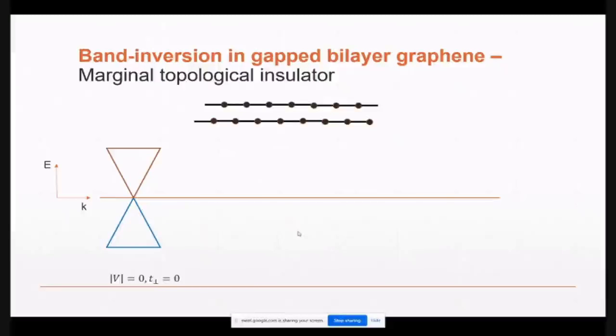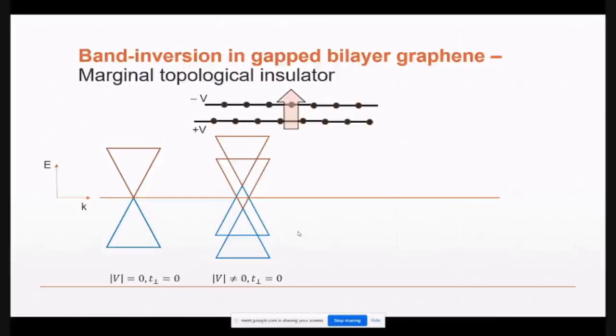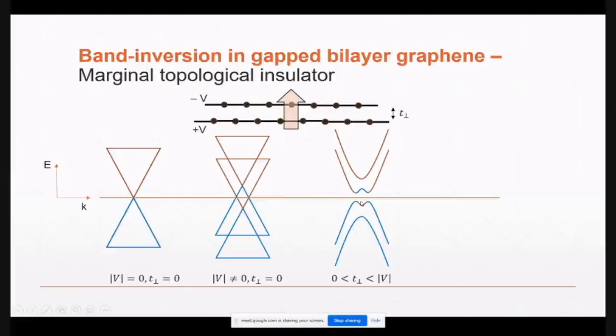For example, you take two layers of graphene, but they are decoupled from each other. Each has a conical band structure, but then you apply an electric field, say, and you shift them because you create a voltage difference between the two. And then you turn the interaction on. If you turn the interaction on, you can create these hybridizations, and then you gap out. Not just do you gap out the bilayer graphene, but you can also see at the bottom, a part of the conduction band goes into the valence band, and part of the valence band goes into the conduction band, which is the phenomenon of band inversion, which is why bilayer graphene is expected to be some form of a marginal topological insulator. Again, there is no spin in it, but that's simply because there is a spinor kind of geometry coming from the two layers.